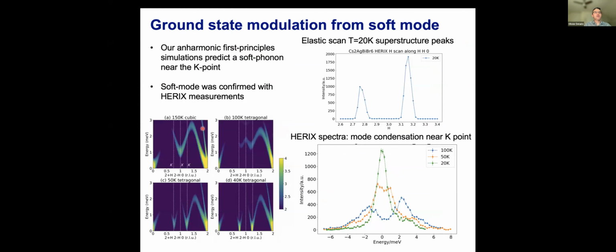So again, on the left here, we have the prediction based on the anharmonic calculations that show that as you cool down in this tetragonal phase, you expect to see soft modes around the K points. And you can expect this would condense around 40 Kelvin or so. So if we measure at 20 Kelvin below the phase transition, we see these relatively weak, but still clearly observed superlattice peaks around the K point wave vector. It seems to be slightly offset from the exact K point, which would be 2.75 and 3.25. I think the figure is slightly shifted here also, so the coordinates probably need to be adjusted, but the actual wave vector of the distortion seems to be closer to 0.2 and might actually be incommensurate. So we're still working to confirm this.